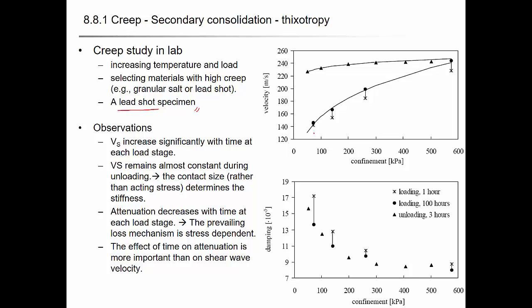And then they increased the confinement and they measured the shear velocity and the damping ratio using the RCTS. You can see here after 1 hour, and this is after 100 hours. So you see an increase in wave velocity and also a decrease in damping during this creep behavior.